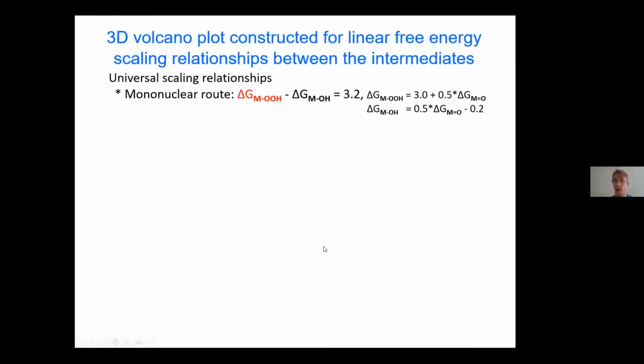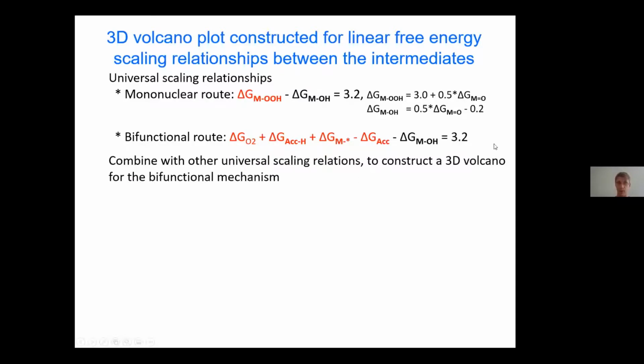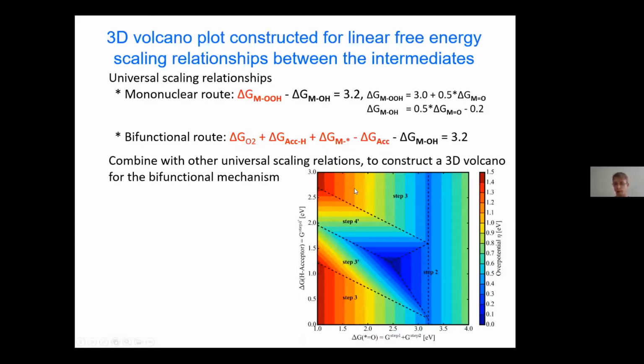So we can also represent that graphically in a 3D plot based on scaling relationships. This is because there are universal scaling relationships between all of the intermediates within the OER process. So here you see these scaling relationships for the mononuclear or single site route. But we can also replace this species within the bifunctional route with oxygen, hydrogenated acceptor site and empty site. And if we then use these scaling relationships, we can come up with a 3D volcano plot.